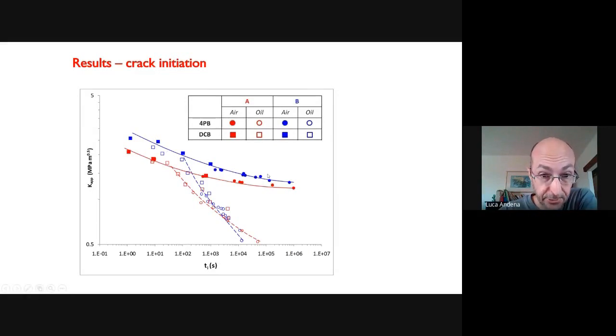And you see that the blue curve is indeed higher than the red ones because the non-ESC resistant material performs better in air. But as soon as you introduce the environment, you see that things change and the red ones eventually become better. Here, other things you can see: all the data fall together irrespective of the configuration. So indeed, these results look geometry independent.